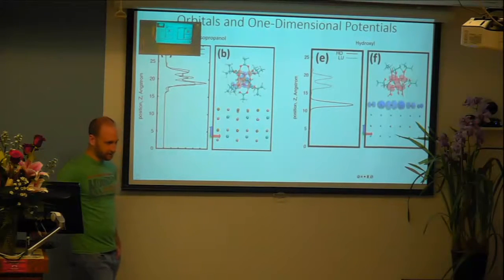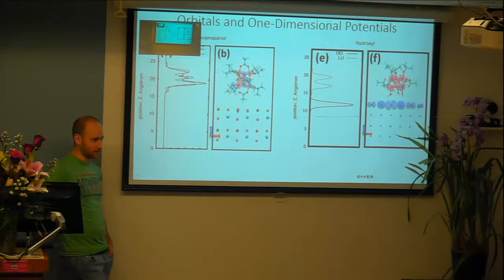Okay, so you're assuming that in the case when your HOMO is on one material and your LUMO on the other material, this transition is optically inactive. You cannot excite such a state because it's optically inactive, right? You can excite the states which are either both localized on a perovskite, and then it would be a perovskite transition, or both localized on a quantum dot, and then this would be your quantum dot transition. And then the idea is when you excite one material, the charge transfer should go not between HOMO and LUMO, but inside the band, from an unoccupied state if it's electron transfer, or from an occupied state if it's a hole transfer.